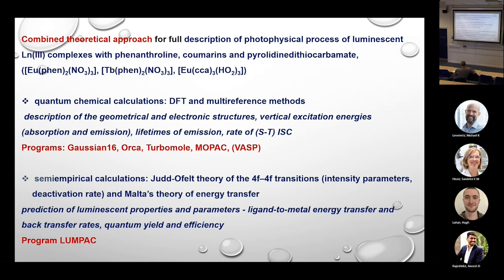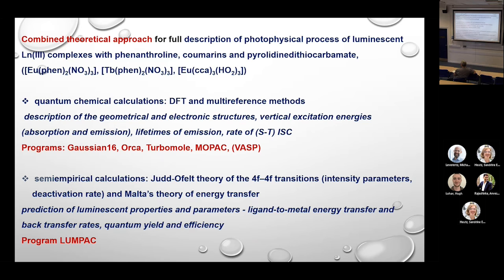So in this approach, we combine quantum chemical calculation for description of geometrical and electronic structure, vertical excitation energies, lifetime of emission, using Gaussian, Orca, Turbomole, and for periodic systems, as I will consider, we use the BAND program. And when we need to predict the luminescent properties and parameters such as ligand to metal energy transfer and back transfer rates, we use semi-empirical calculation based on Judd-Ofelt theory of the f-f transitions and Malta's theory of energy transfer. The program which we use is LUMPAC.